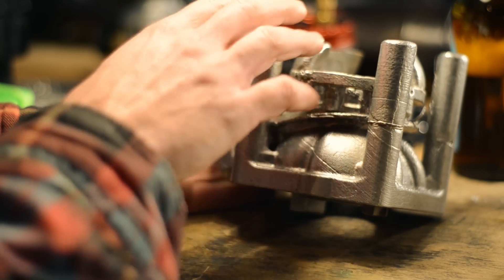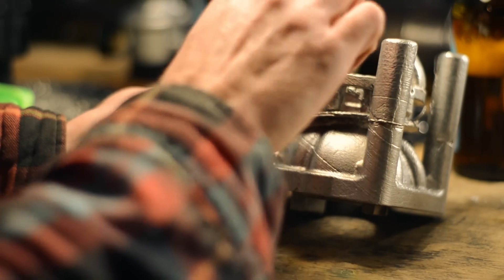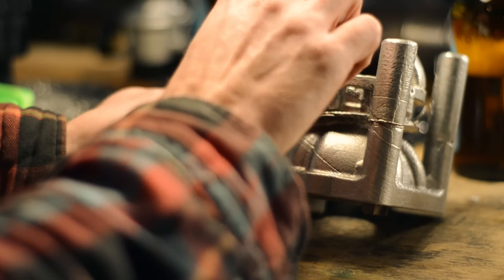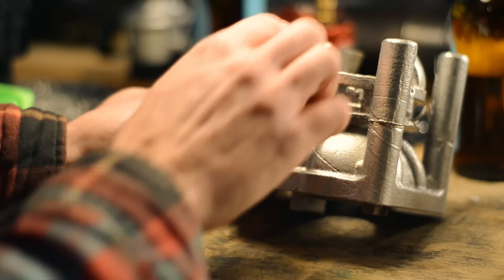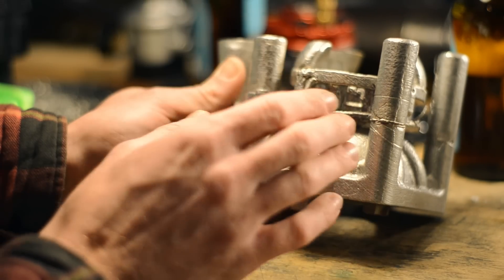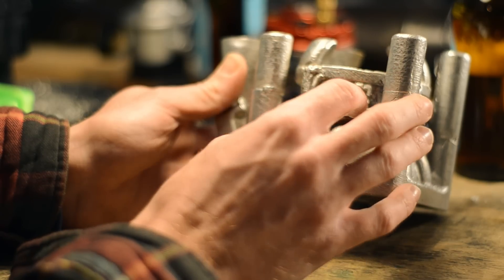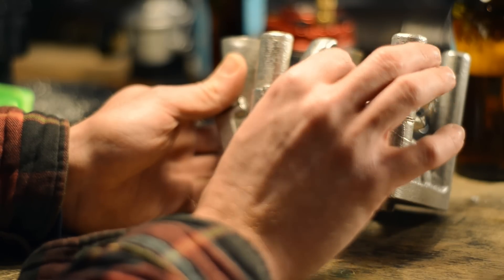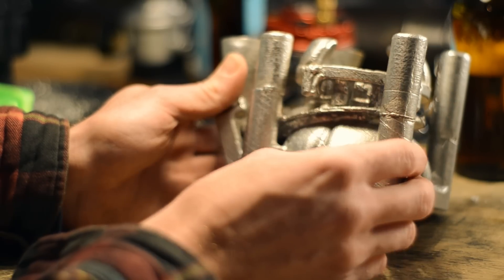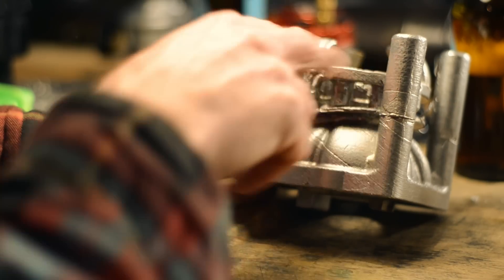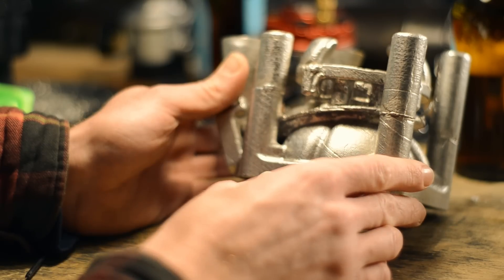I think that's down to my really short sprues or risers. They were supposed to be much higher, but I ran out of metal. Probably there wasn't enough pressure to fill in the thin sections, and also the top part here, probably that's the main issue with this whole thing here.